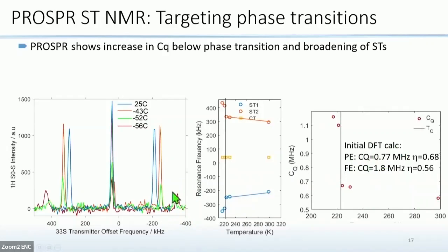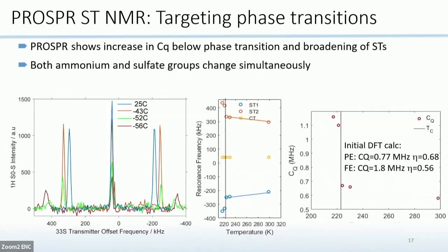And additionally, we also saw some broadening of the satellites by PROSPR, and we think that maybe it has something to do with the loss of inversion center in the structure. And so at least from these measurements, we can see that both the ammonium and sulfate groups change simultaneously in a very similar fashion.